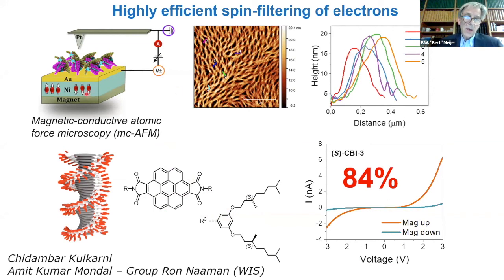Then with a magnetic field AFM, you do the following. With a magnet, you polarize the spins in the nickel ferromagnet. You have gold, the spins go through, and then you measure the IV curve. And then you do it for the spins up and down. And much to our surprise, the selectivity is 84%. And for chemists, I think you can compare it a little bit to enantiomeric excess. So there's a big preference for one spin going over the other.